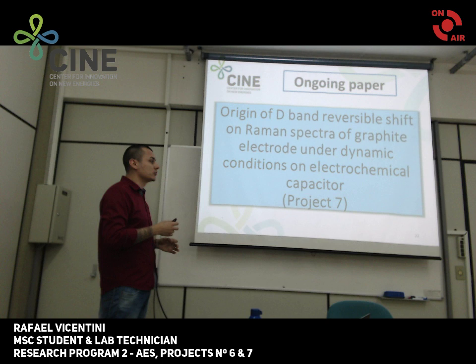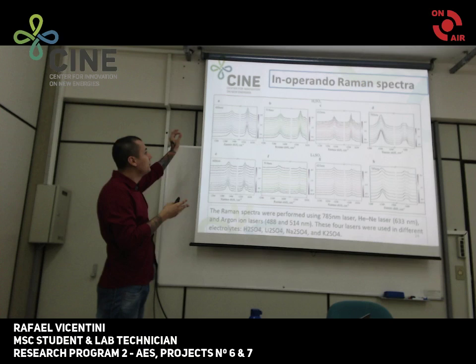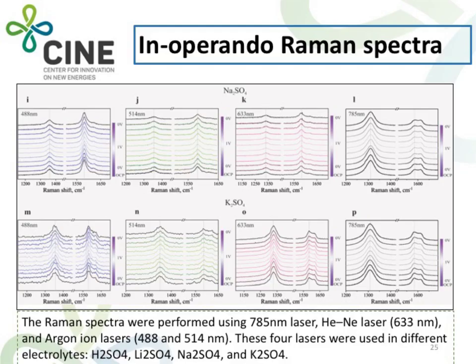As you can see, from figure A to D we have the Raman spectra acquired using acid sulfate. From figure E to H, we have the Raman spectra using lithium sulfate. From figure I to L, we have the Raman spectra using sodium sulfate. And lastly, from figure M to P, we can see the Raman spectra using potassium sulfate. But maybe you can ask me again, why have we been using 4 different lasers and 4 different electrolytes? We have been doing that just to verify whether the ion size or the laser frequency can affect the D-band shift on Raman spectra.